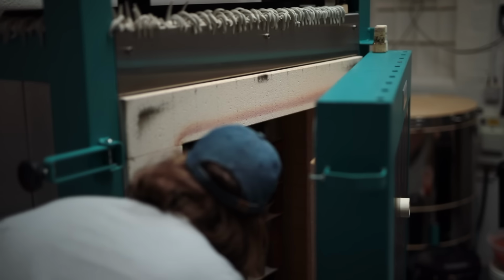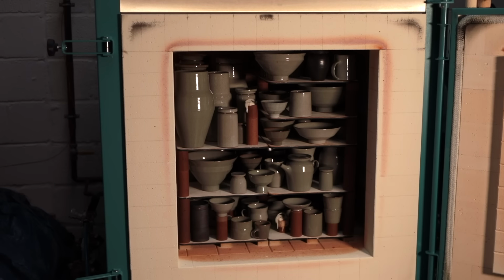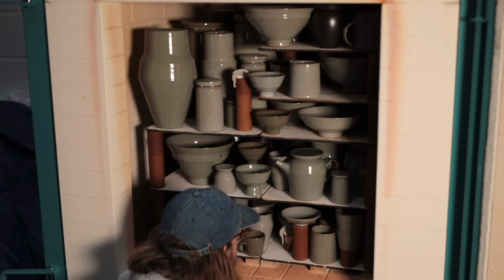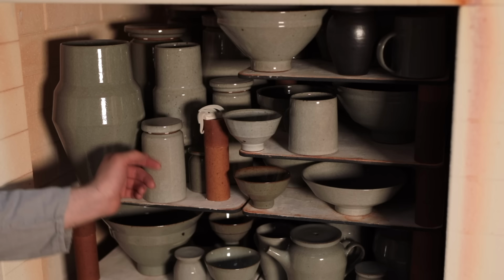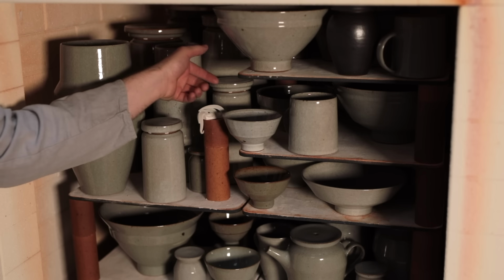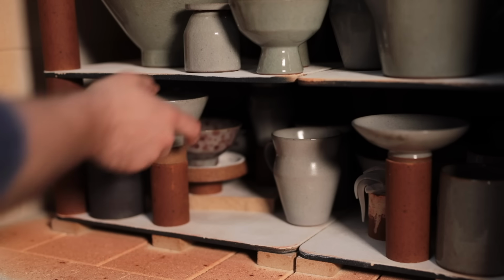And from this point, the kiln takes about 2 days to cool down. The door is then cracked open, and finally I can look at those two tests. The firing was decent overall, but it was perhaps a little bit cold in a few spots on the bottom shelf, which results in a slightly matte surface on the glaze.